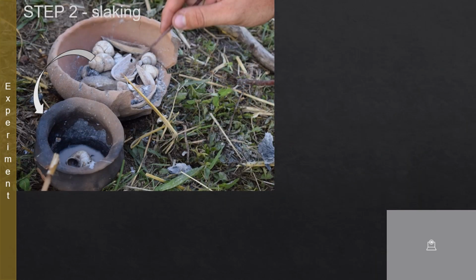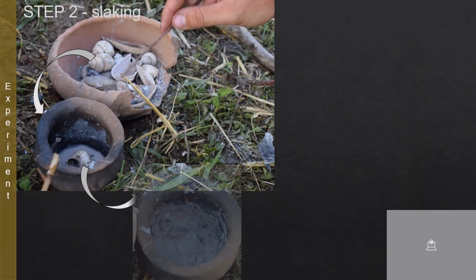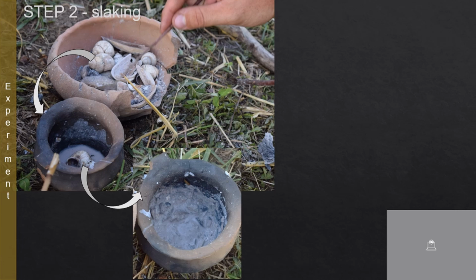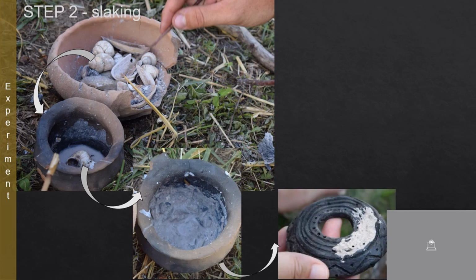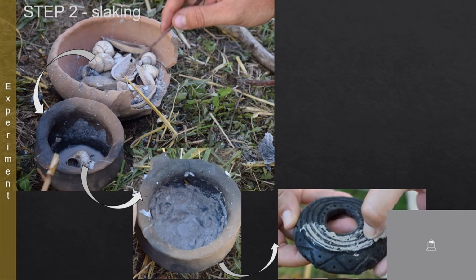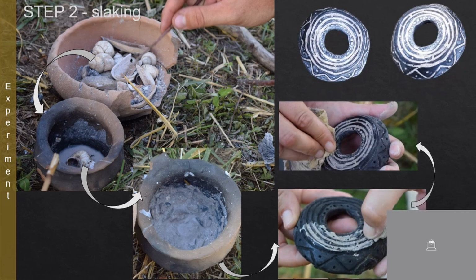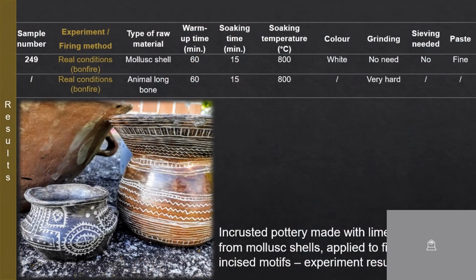Shells remained whole, but when water was added, they quickly disintegrated into a thick grayish-white paste. After mixing, we obtained a homogeneous paste that was easy to apply to pre-fired pottery. After 24 hours, the material hardened into a durable lime plaster, keeping the inlay intact even after washing.